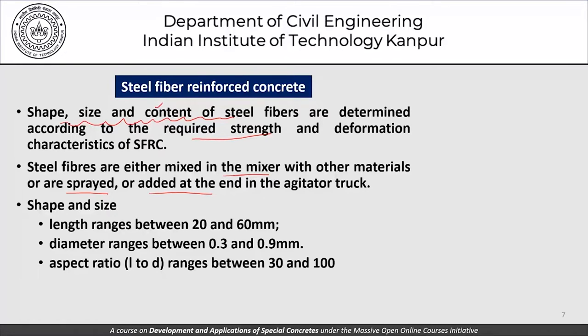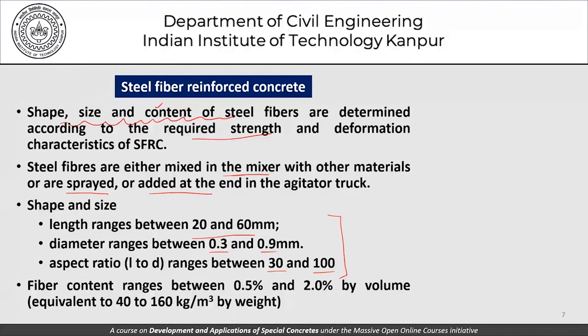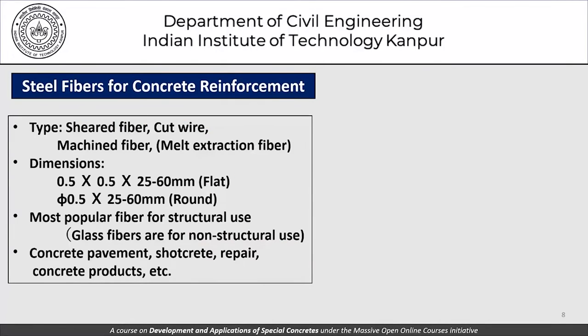As far as shapes and sizes of steel fibers are concerned, length usually varies between 20 to 60 mm and diameter from 0.3 to 0.9 mm, giving aspect ratios between 30 and 100. The fiber content ranges from 0.5 to 2 percent by volume, equivalent to about 40 to 160 kg by weight. There are different kinds of fibers: sheared type, cut wire, and machine fibers, among others.